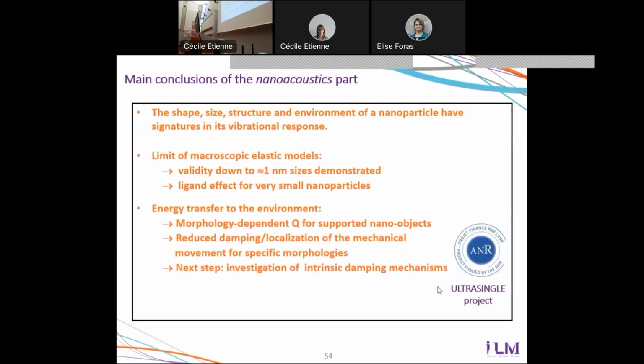Okay, so that's the end of the acoustics part. As you see, elasticity is very robust for very small nanoparticles. They still can be described using a model that was developed for describing the vibrations of planets, for instance. And regarding energy transfer to the environment, in the last years, we have better understood the vibrational coupling between a nanoparticle and its substrate, and we have partly managed to increase the associated quality factors.